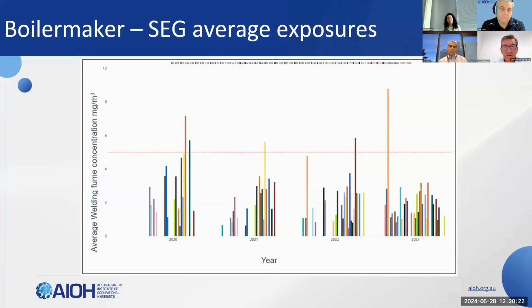We then move to the next slide. You can see there, if we superimpose the line that represents the current limit of 1 milligram per cubic metre, all of the sites except for one now start exceeding the exposure limit of 1 milligram per cubic metre. If we then also apply the rule of thumb for good hygiene practice, and that is that we control exposures below 50% of the limit, you can see that all of the mines will be above that exposure limit action level of 0.5 milligrams per cubic metre.